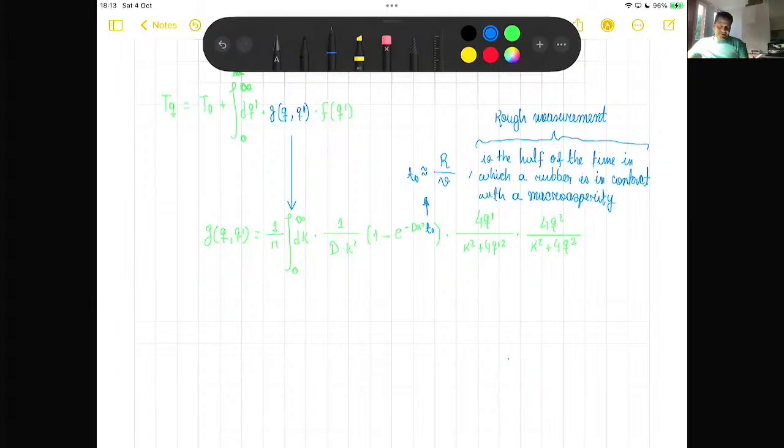From the single asperity case, we also took advantage of the definition of the elastic modulus, which is E of omega and T, T from temperature, capital letter T. But for this case, we have a constant B(T) times the elastic modulus in function of a frequency, a constant A(T), and a background temperature T0, capital letter T0.